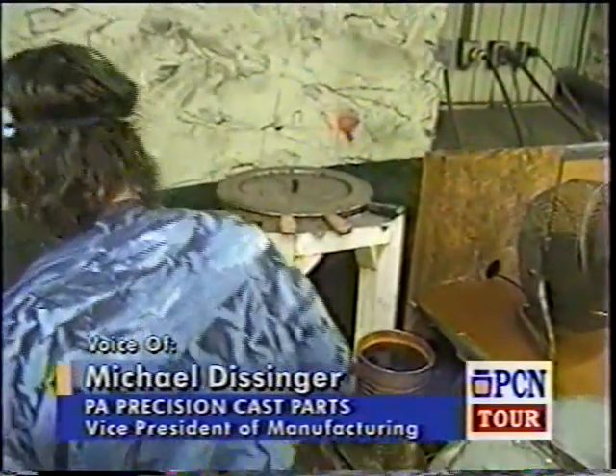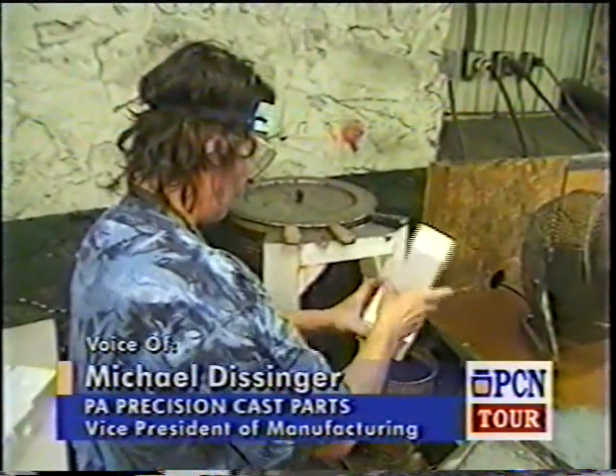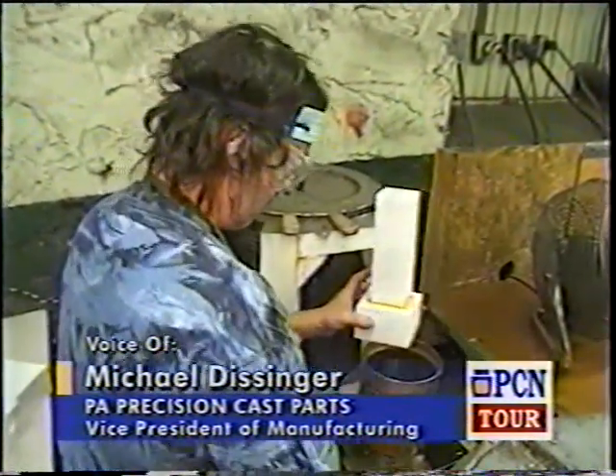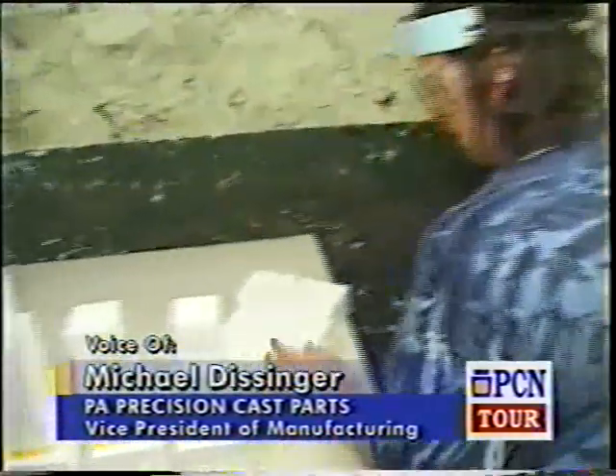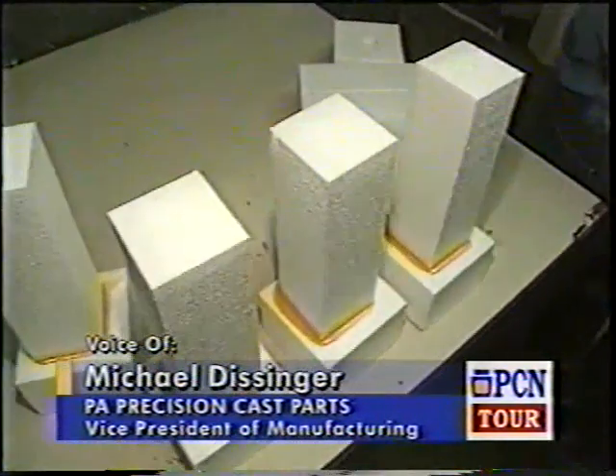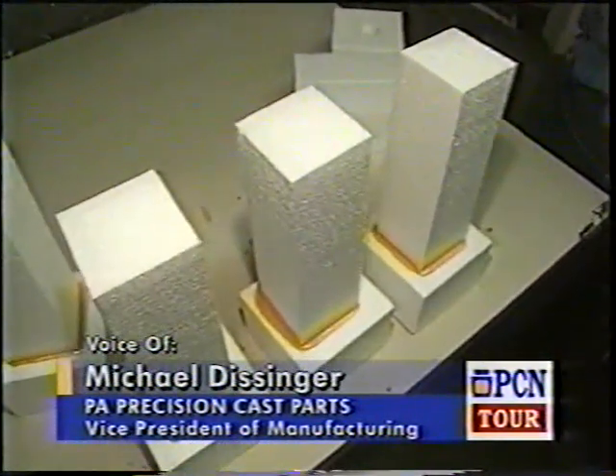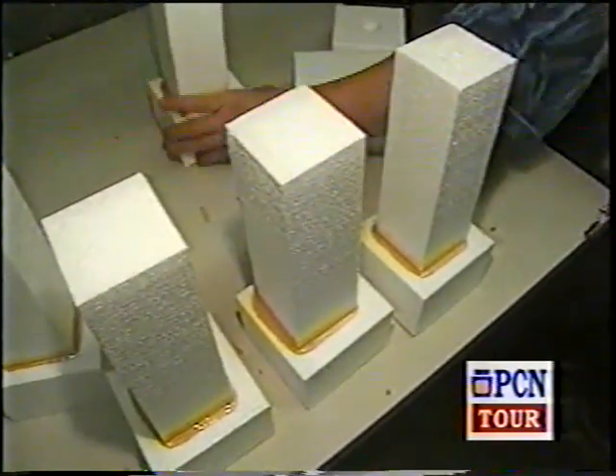The styrofoam is used for several reasons. One, it's more economical than using wax spruing, and two, because we're a hand-run shop, it's much lighter for the operators that will be handling the mold as it's being built. The styrofoam that we use is cut specifically for the individual part that will be assembled to it. We glue them together, putting a pouring cup on the top.